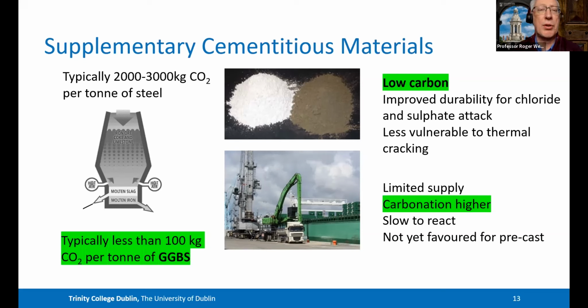Not all the properties are advantageous. It carbonates at a faster rate. And therefore, if you don't plan and design for that, you could have a durability issue, which again would give rise to long-term repair and therefore carbon issues. And it is imported, but used very successfully in Ireland. It's not favored for precast, and precast, of course, is something which is receiving a lot of attention because of its efficiencies, and I'll say a little word about that, but it's not favored there because of the productivity problems due to the slower rate of reaction of GGBS.